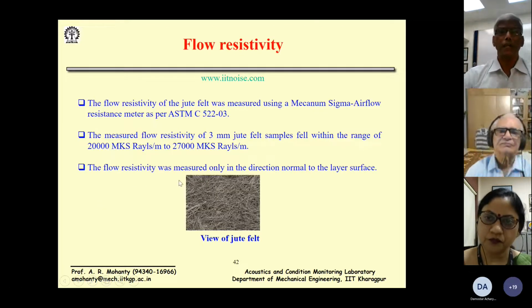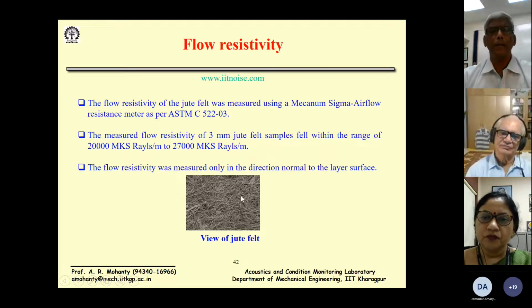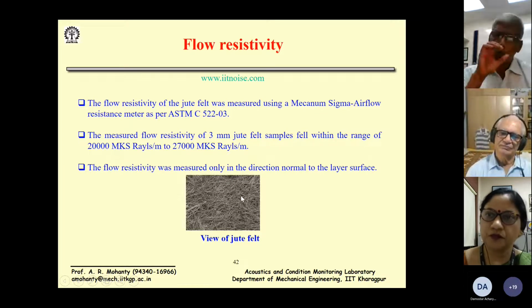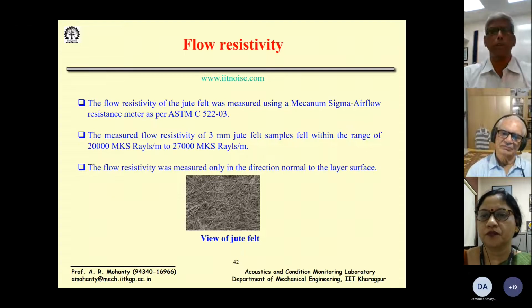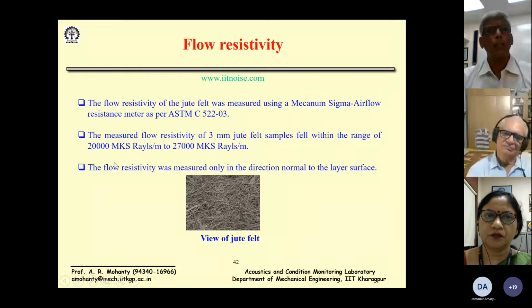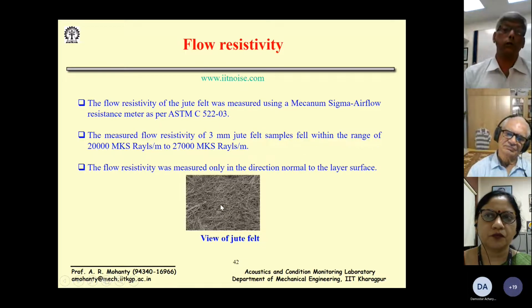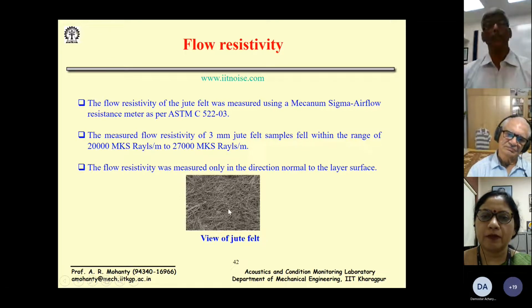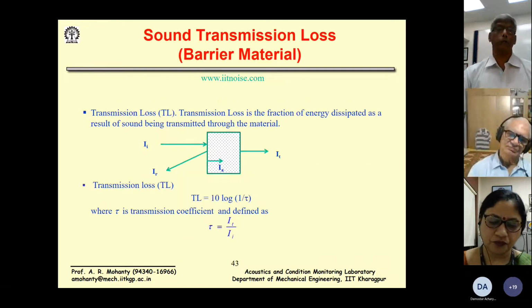And another thing I must tell the students who are here: for any fibrous material, if you blow air through it, there will be a pressure drop. And this pressure drop to the velocity ratio is something known as the flow resistivity. And those of you who do not have such expensive equipment to measure the sound absorption or the transmission loss, you can, for fiberglass material, from empirical relations, once you know the flow resistivity, which is very easy to measure even with a manometer and an anemometer, find out the sound absorption coefficients.